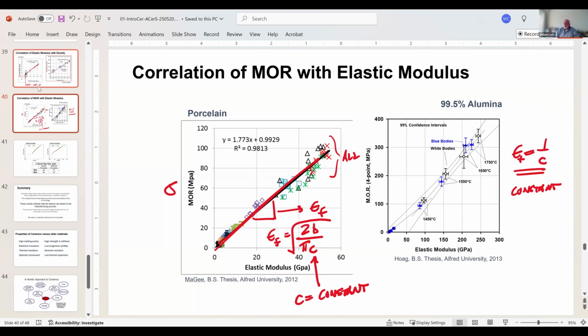And so that argument that flaws do not change with densification is a huge deal, because that means that the flaws that we are dealing with in the system are the flaws that we introduced in the process, and that sintering does not eliminate those flaws. All sintering does is it improves my elastic modulus.